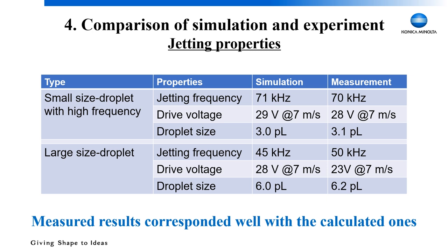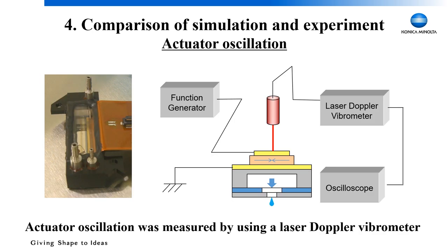Next, to investigate the specific actuator properties, we observed the actuator oscillation properties by laser Doppler vibrometer. This is the observation model, and we used a glass plate as the top cover of the prototype head, and that enabled us to observe the actuator oscillation while the printhead was jetting the droplet.